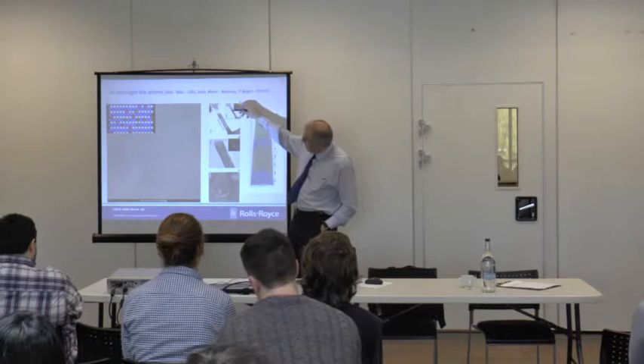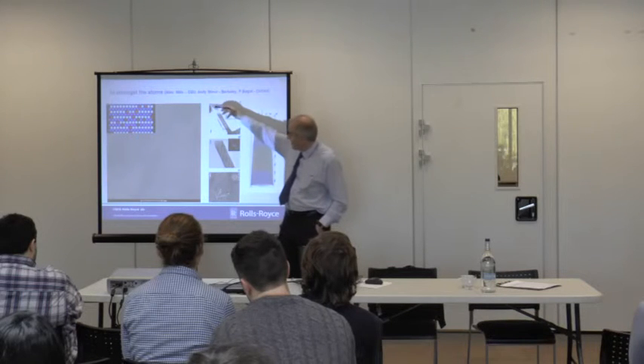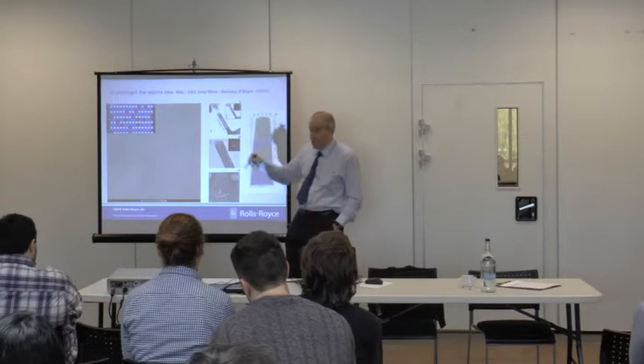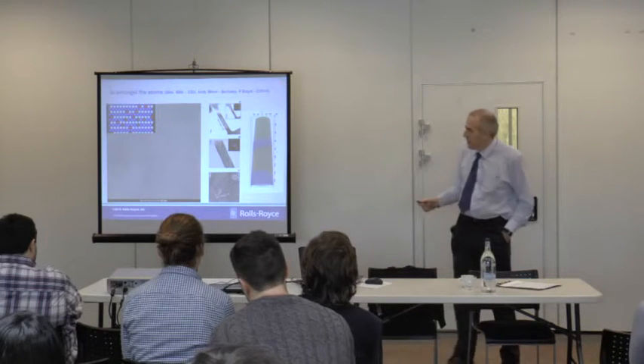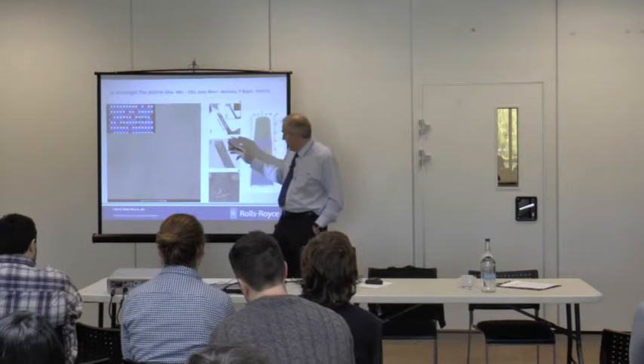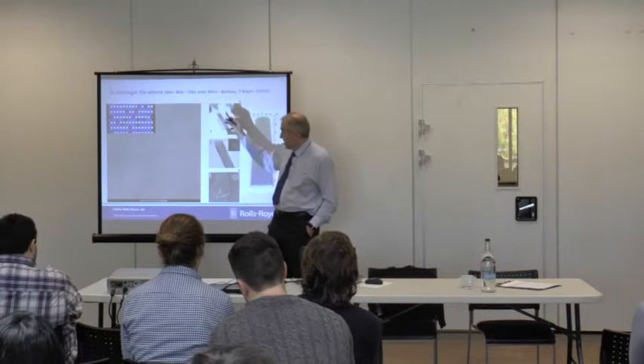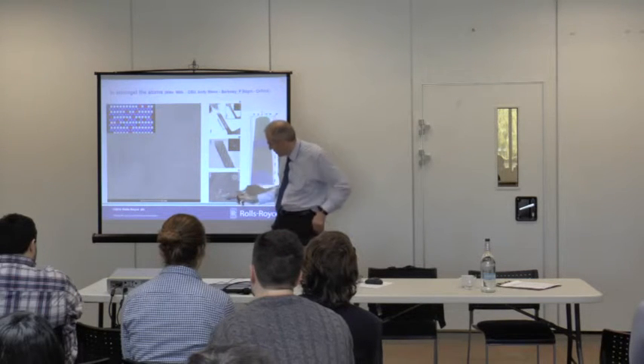They can pull them so that you get a stress strain curve, which is pretty neat in its own right. That's a 200 nanometer scale bar there. But they can do it inside an ultra-high resolution transmission electron microscope. So you can actually watch the dislocations moving around in there, and you can relate that to what's actually going on in the material as to whether we're forming things called twins, which is a crystallographic shear process. So we've got micro twins in here.